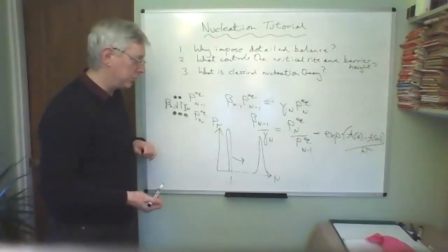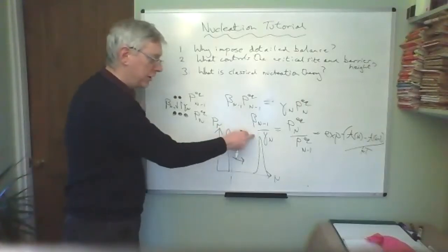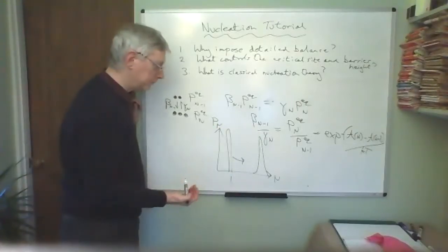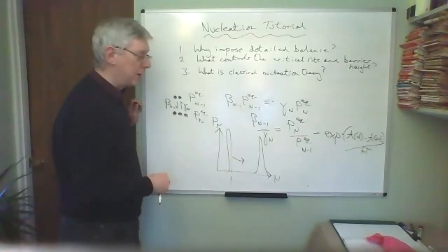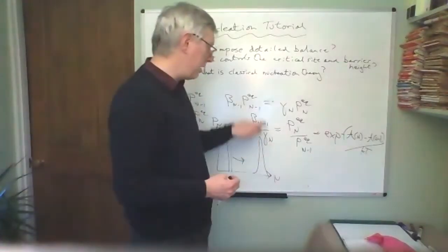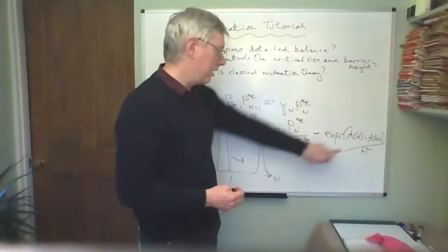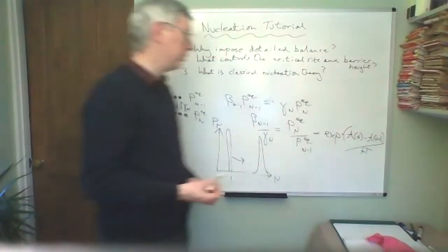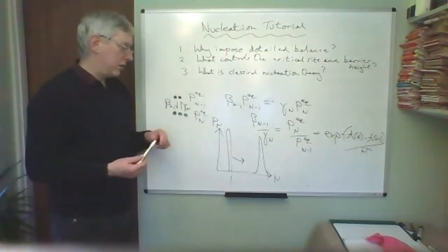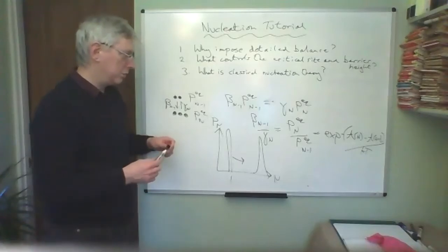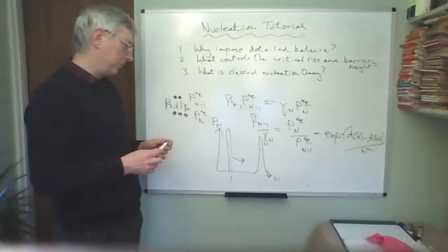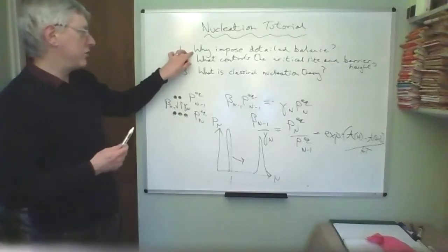A nucleation event has happened. And we can use these rates in the Becker-Döring equation to evolve probabilities. And we know something about the ratio of these rates from equilibrium statistical mechanics. That's why we are bothering with this availability potential and these equilibrium rates. Okay, so that's the question and that's the answer.